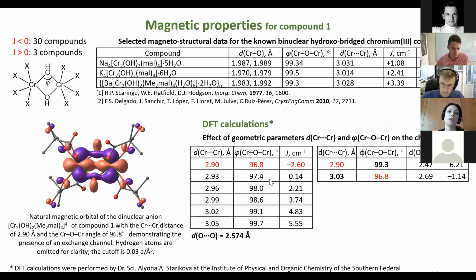The search of the literature data on chromium complexes containing the dinuclear hydroxo-bridged unit shows that antiferromagnetic exchange interactions dominate in the majority of these complexes. Ferromagnetic exchange interactions were observed only in 2 known malonate complexes, like in our complex 1. An analysis of the literature data shows that the character of the exchange parameter J depends on the chromium-chromium distance, the chromium-oxygen-chromium angle, and the chromium-oxygen bond length.